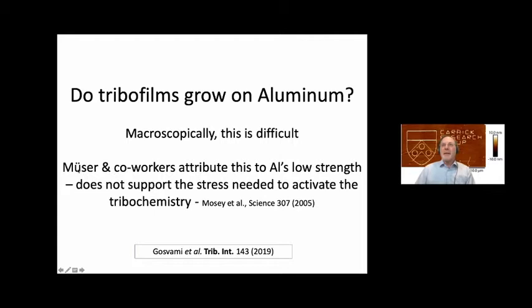So Martin Müser's work back in 2005 attributed this lack of growth on aluminum to a mechanochemical effect. Aluminum is a soft material. It will give way and deform before you may be able to reach the stresses that are needed to cause the tribochemical growth to occur. Again, exponential dependence on stress means an exponential dependence on the strength of the substrate and the stresses it can support. So that's one possibility.